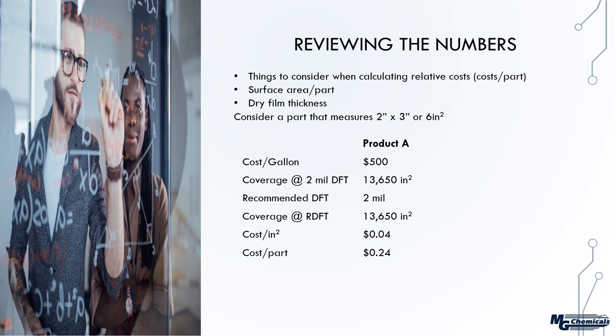We take an off-the-shelf product, product A, at a cost of $500 per gallon. Now the coverage at a 2 mil dry film thickness is 13,650 square inches. We calculate these efficiencies, so that is something that we provide. That is found in our technical data sheets, and we try to standardize it over the same dry film thickness. So here we're going to use 2 mils. Now let's say 2 mils is also the recommended dry film thickness, meaning that in our opinion, you get maximum performance with 2 mils of dry film thickness.